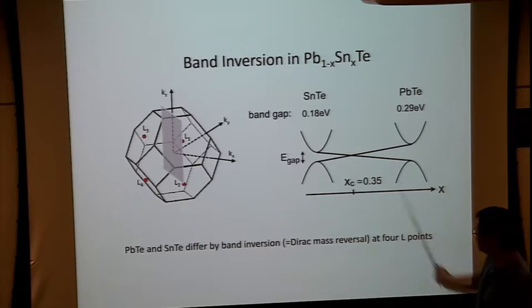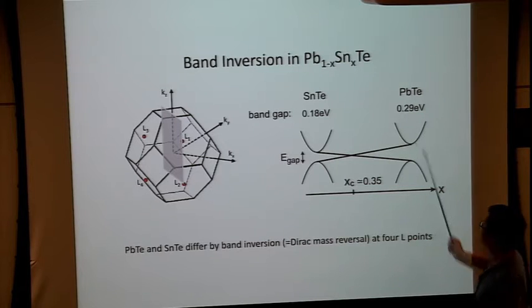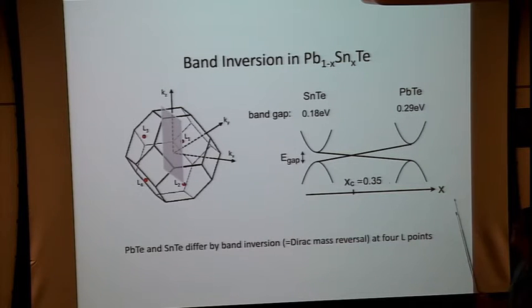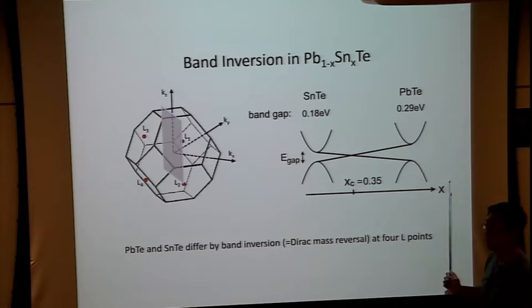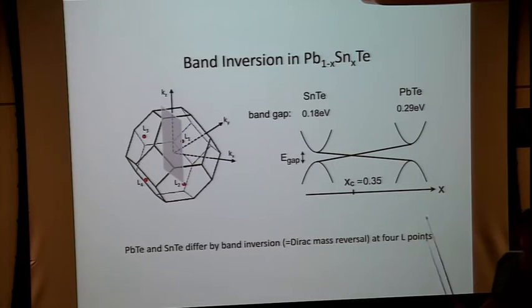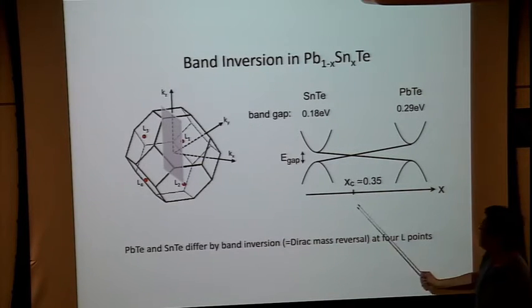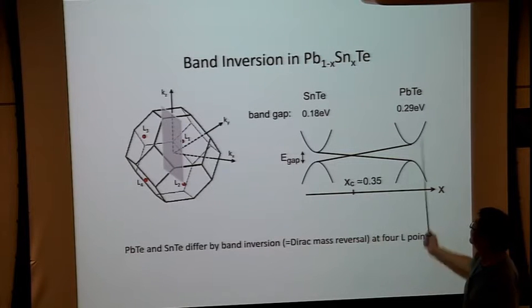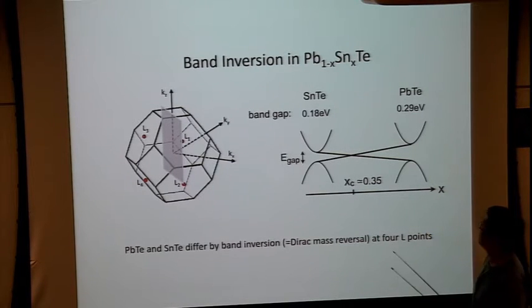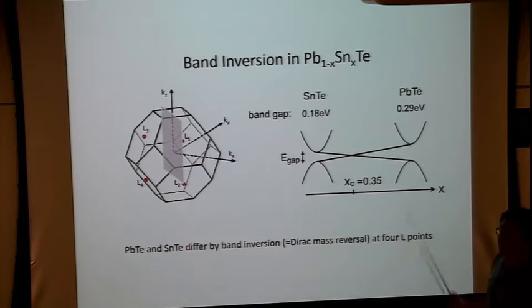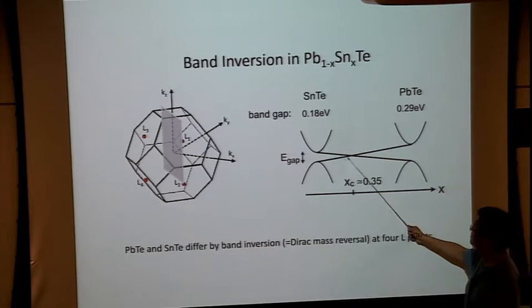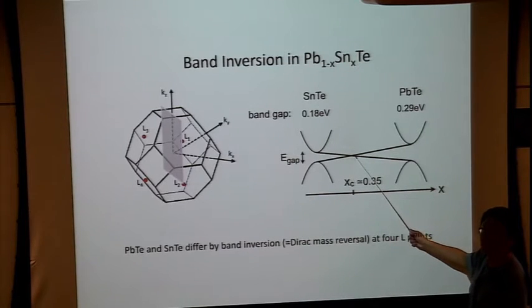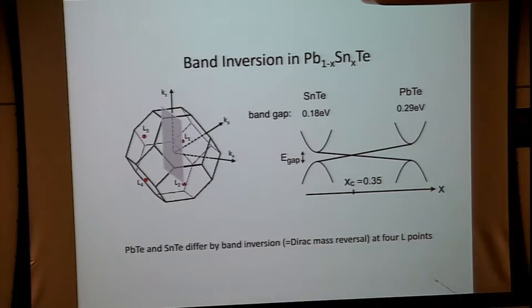It has been known for decades that tin telluride and lead telluride are both narrow gap semiconductors with band gaps that are comparable. And also it's known that the two elements, lead and tin, can mix with each other to form an alloy, lead tin telluride. As a function of this alloy composition, when x, the tin composition, is around 0.35, the band gap of the alloy goes to 0. And after that, the band gap increases again.